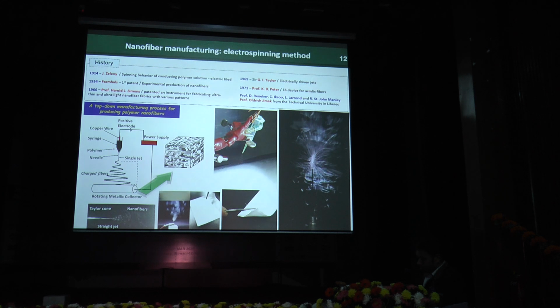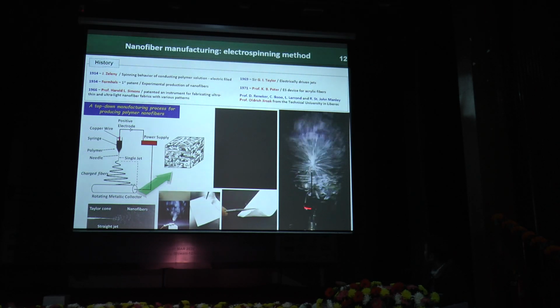So this is the video I can show you, so you can understand. This is the polymer solution. When you apply high voltage, the polymer solution gets dragged into nanofibers. You see how the nanofibers are formed from the droplet of the polymer solution. The mechanism is very simple. When you apply sufficiently high voltage, the polymer solution gets charged, and when the electrostatic repulsion counteracts the surface tension, the polymer solution at the tip will be stretched into fiber form. Eventually the solvent evaporates and the nanofibers are collected on the metallic collector.